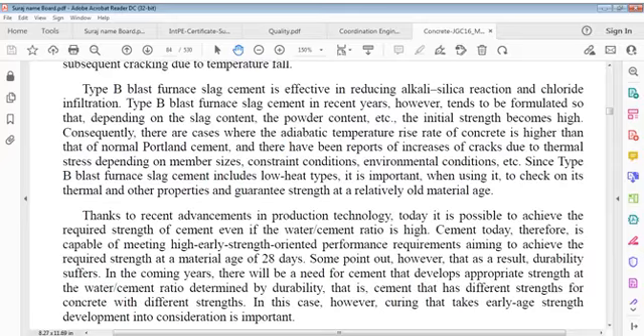It's generally reported that convergence time of maximum adiabatic temperature by adiabatic temperature rise takes between 5 and 7 days. In this study, however, the phenomenon that convergence time decreases by use of high strength concrete was confirmed. It was observed that increasing water binder ratio and using admixture tend to decrease maximum adiabatic temperature and temperature rising velocity at early ages.